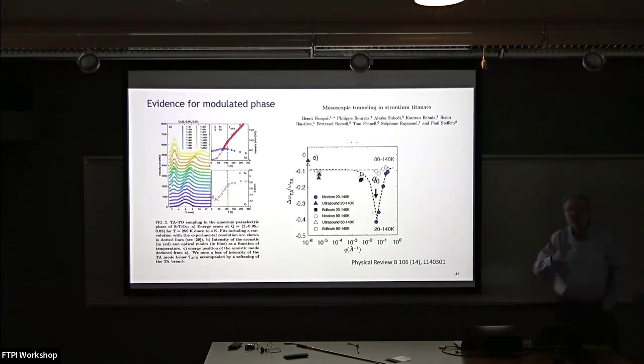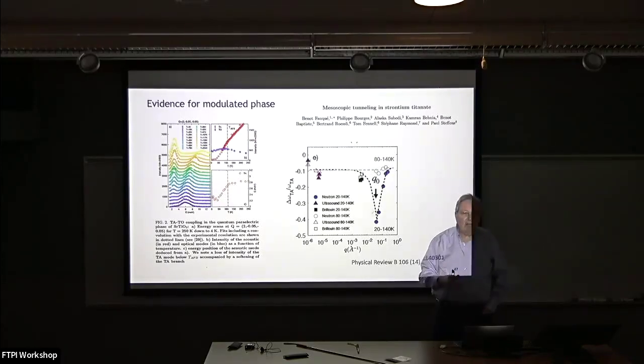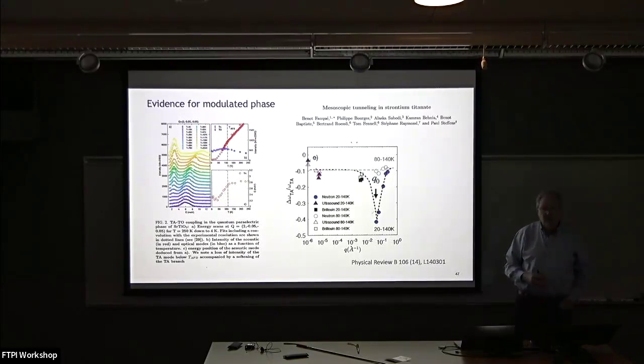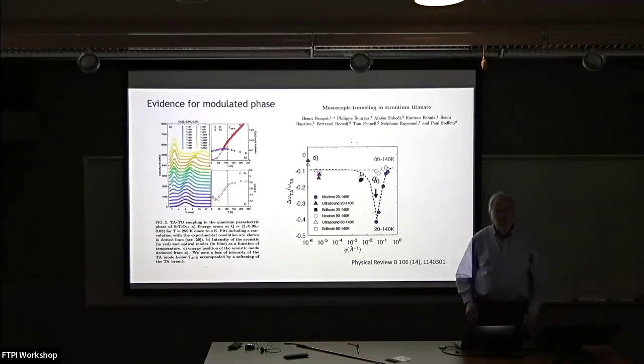There's an interesting story associated with that issue. Strontium titanate is a non-correlated material. It's something where ab initio methods in principle work very well. So if you ask ab initio calculators to calculate the structure of strontium titanate, they in principle can do it, but they have found it very hard. There are even some papers which got answers which basically say that the system is disordered even at T equals 0. I don't quite know what happened to the third law of thermodynamics with that. But it turns out to be very, very difficult to stabilize these phases in those calculations. And the reason is presumably that if something is producing a very long period of stability, you need a very large supercell to capture it.